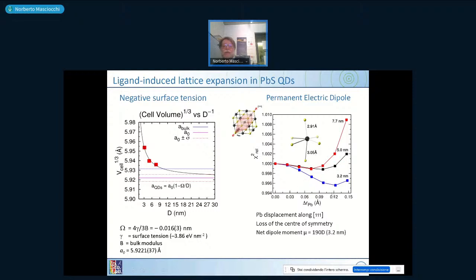What does distortion mean? It means that out of six sulfides, 3 become shorter and 3 become longer. So you have the distortion of a lead, which is moving outside the center of symmetry and has the 6s2 lone pair, which is a non-inert lone pair, protruding out from the lead. Lead is not anymore a sphere. Of course, if you lose the center of symmetry, you induce a dipole moment, which was calculated for the 3.2 nanometer to be very high, 190 debye.